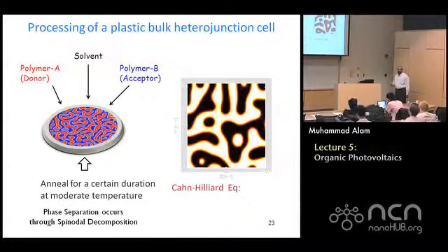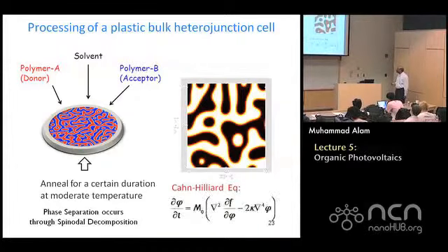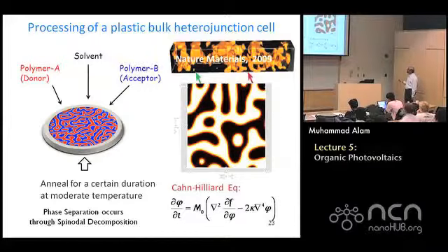I'm going to very quickly tell you what equation was used, but not explain it very much. The equation that was used was sort of a diffusion equation of some sort. Here is the surface tension, and here is the mobility of the polymers, how they can diffuse across one another. So you can solve this equation, and I think there are recent experiments like this in Nature Materials where they use that high Z contrast.